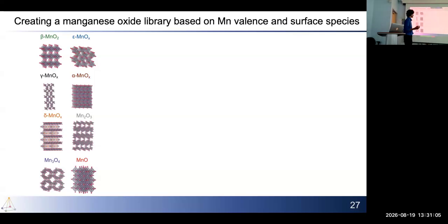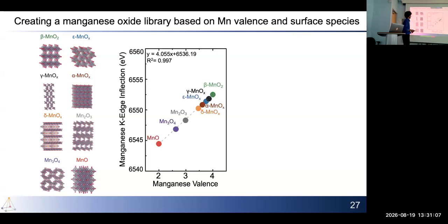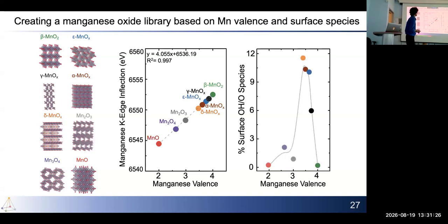To optimize the reaction kinetics and form a descriptor, we looked at manganese valence, which is a much easier metric to compute relative to other electronic structure parameters. We used X-ray absorption spectroscopy to calculate the manganese valence, and we also used TGA, thermogravimetric analysis, to quantify the amount of water and oxygen in these species.